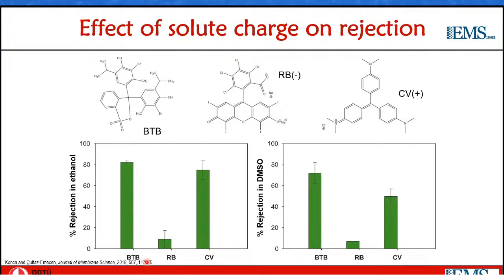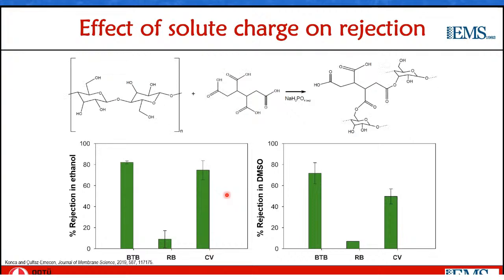And then what we saw was that when you compare these two solvents, for the same dye, the rejections were quite similar. But although the sizes of the dyes were more or less the same, the rejections were affected by the charge of the dyes, where the negatively charged dye was not rejected, but the positively charged dye was. And then we treated the cellulose membranes with the polycarboxylic acid, which cross-links the hydroxyl groups of cellulose, and then leaves pendant carboxyl groups that give the membrane a negative charge.